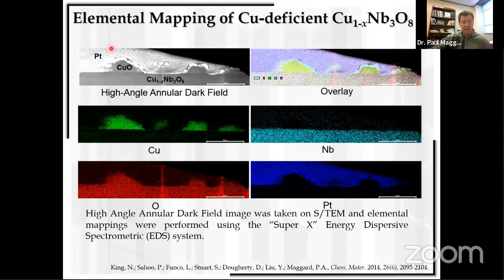And so this is something that was done within the electron microscope. And then we image the elemental composition for the copper oxide, these islands, right? So you can see they're all green, they're all copper with no niobium in them, okay? And then below that copper oxide, we still have the 138 composition where you can see below it here, it's niobium, oxygen, and much smaller amounts of copper.